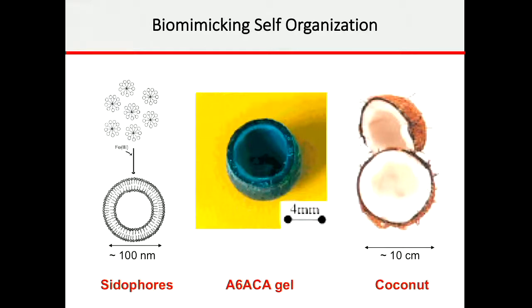Now the question is, why does it happen? When we did the analysis, we saw a hard core outside, followed by a softer inside. So what happens is, you have this acryloyl 6-aminocaproic acid polymer, you put it in copper chloride solution, the cupric ions start diffusing, and at the interface, they lock in all the carboxyls, which are hydrophilic. So if all the hydrophilicity is knocked out, you have a hydrophobic surface. So you have a cylinder with a hydrophobic surface in water. So what does it do? It tries to minimize its surface energy. And what is then the form? It has to be the sphere. So it turns into a sphere. But why the hell should it convert into a coconut-like structure?